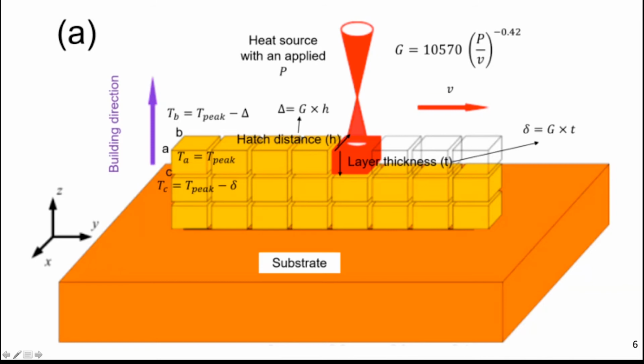Now, the parameters to consider are this hatch distance, so what is the distance between adjacent lines that are scanned? And the layer thickness, because when I move the powder bed downwards, there's a thickness to the layer. You can imagine how important this is for many reasons. If the hatch distance is massive, I don't melt the material properly because I leave spaces without melting. And the same can be said about the layer thickness. This hatch distance can be calculated, I will not elaborate how, but I'll call it uppercase delta, and the layer thickness, lowercase delta.